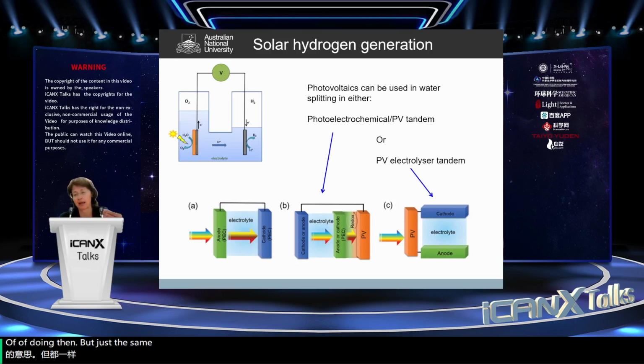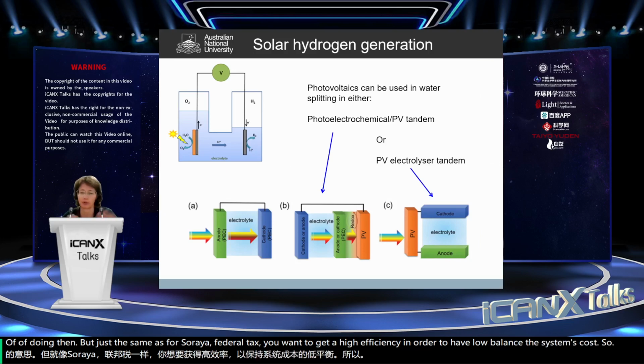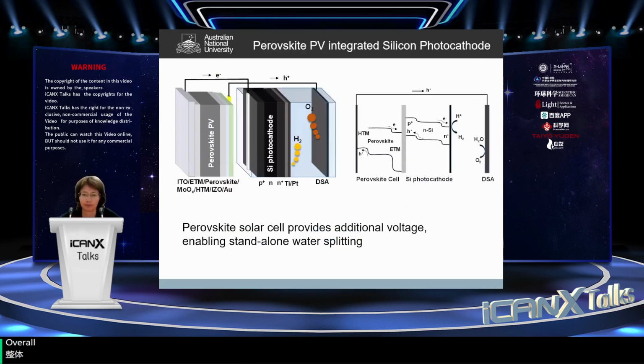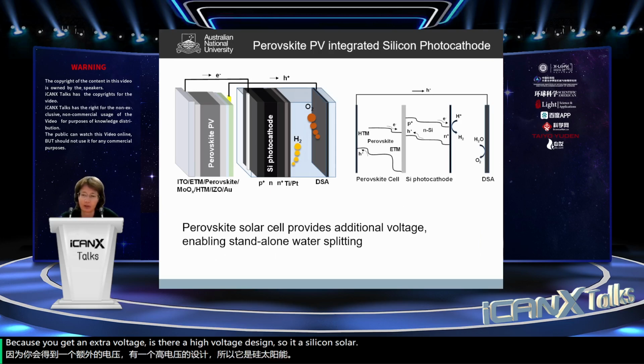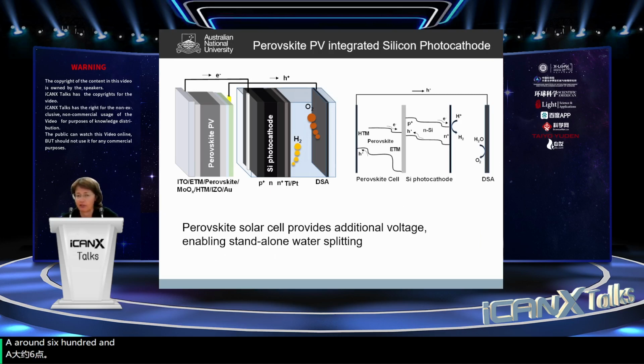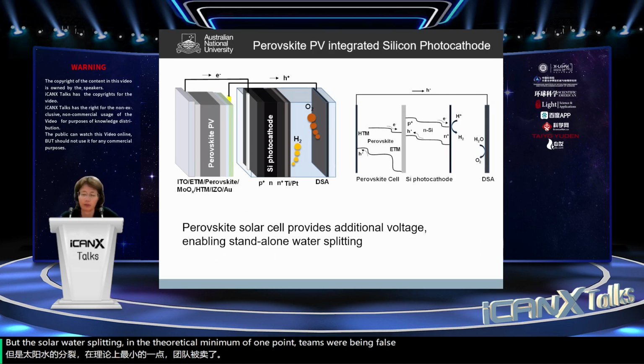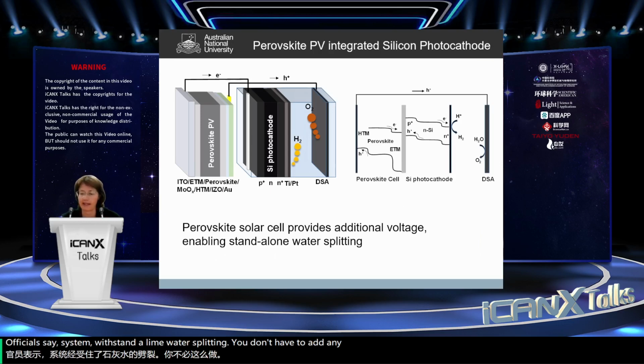But just the same as for solar photovoltaics, you want to get a high efficiency in order to have low balance of systems costs. So you need high efficiency if you want to have low cost overall. So tandems with perovskites are particularly attractive because you get an extra voltage. They're a high voltage design. So a silicon solar cell is only going to give you around 650 millivolts, something like that. For solar water splitting, there's a theoretical minimum of 1.23 volts, and then you need a few extra 100 millielectron volts to take account of the overpotential. So by adding perovskite photovoltaics, you have extra voltage, and so with that, you can potentially get a high efficiency system with standalone water splitting. You don't have to add any extra voltage.